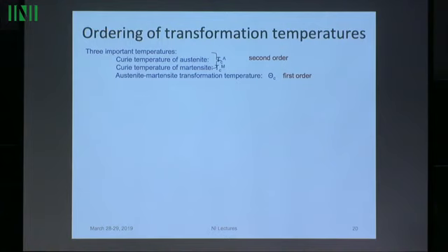This involves phase transformations in which, in the ferromagnetic case, one phase is a strong magnet and the other phase is non-magnetic. Okay? In some of these transformations, you can make lambda 2 very close to 1, so you can have quite low hysteresis. I'll show you some examples later.